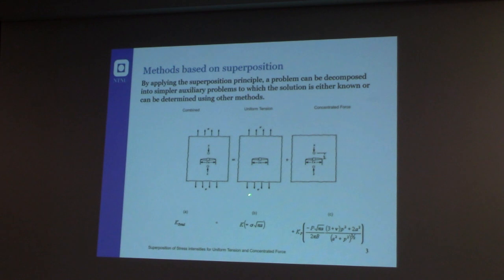If you have the closed form solution for each of the two sub-models, then the combined stress intensity factor is the sum of the first term plus the second term. So the advantage of having a linear elastic model is the possibility to always use the superposition principle. You don't have to repeat the model. Also, if you change the stress level by 2 times, the stress intensity factor increases 2 times, so you don't have to remake any kind of model. So superposition and scalability with respect to the load are a very important effect of using a linear elastic hypothesis in your modeling.